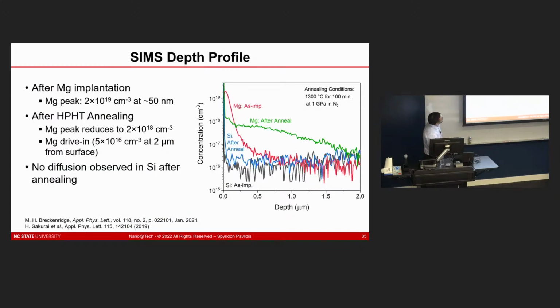Now, SIMS here is also something that's very interesting, especially from an electrical design perspective. You have this very sharp magnesium implantation distribution here, which is SIMS captured on the sample right after implantation. And you can see that we designed this for a shallow implantation depth. We basically were trying to use this for contact layers.